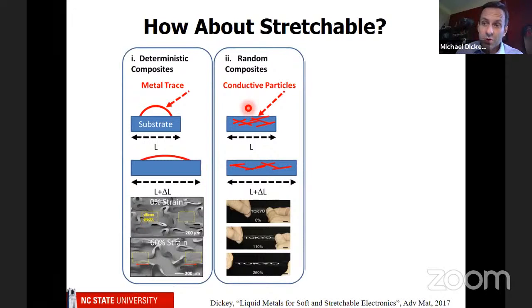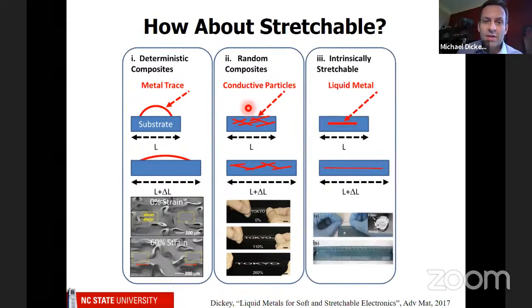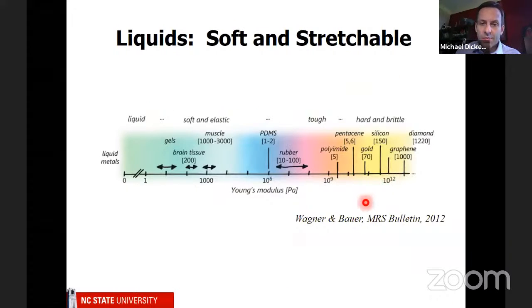So there's a third approach, which is what I'm going to talk about, and that is to make materials that are intrinsically stretchable, like liquid metal. If you have your conductor made out of liquid metal and you stretch it, you can make it longer without changing the conductivity. So why do we pick liquid metals? Because they're soft and they're stretchable.